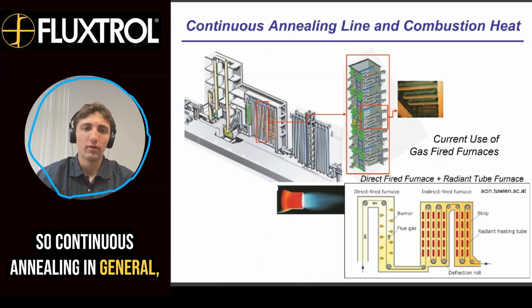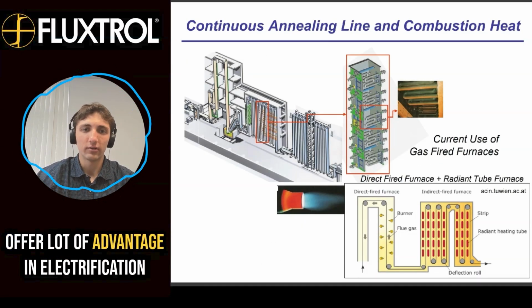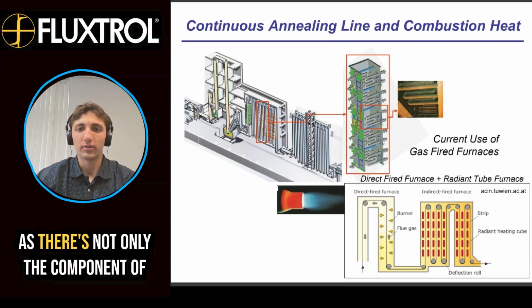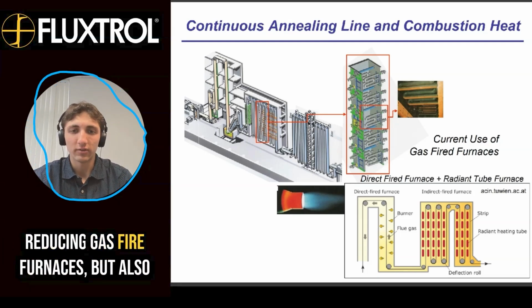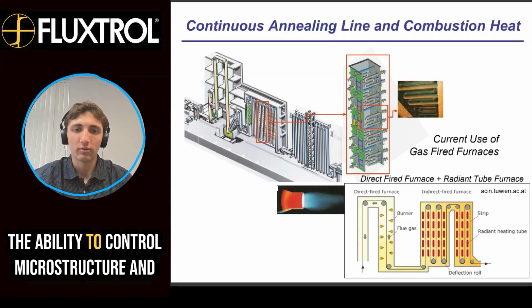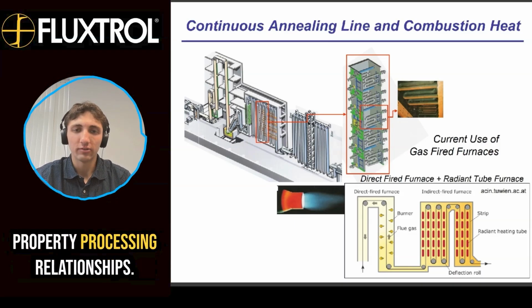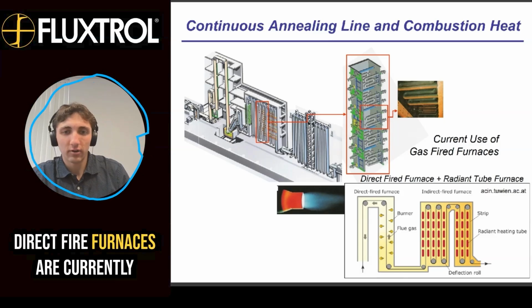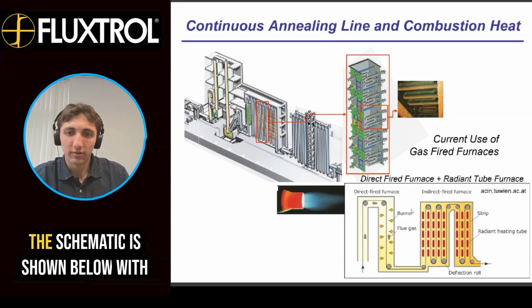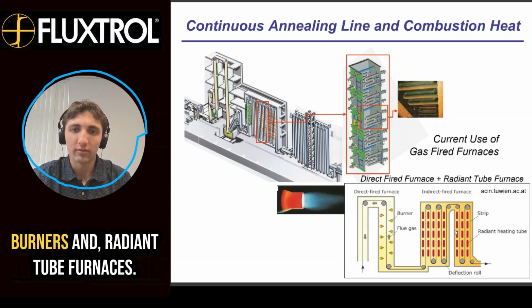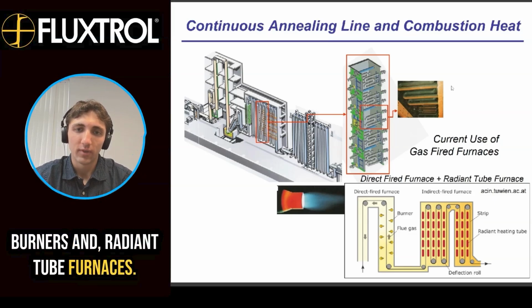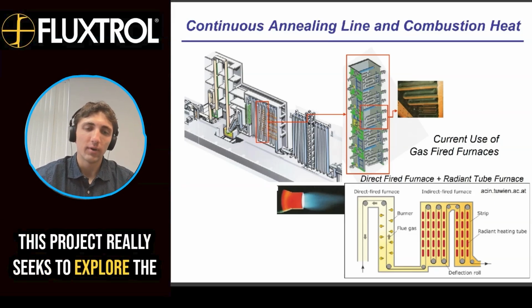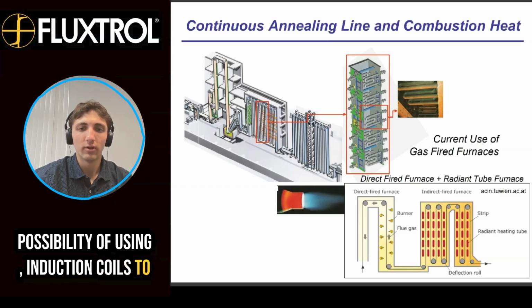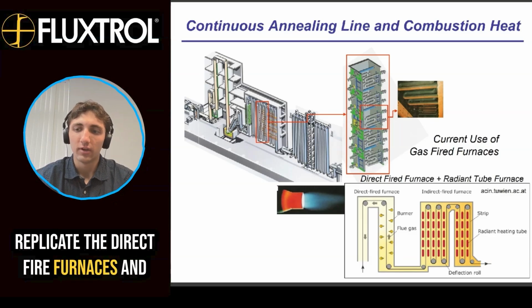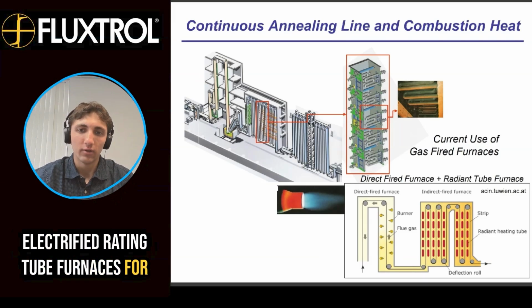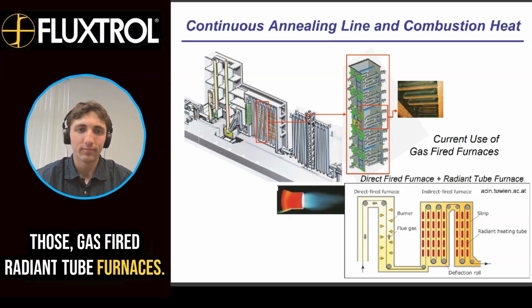So continuous annealing lines in general offer a lot of advantage in electrification, as there's not only the component of reducing gas-fired furnaces, but also the ability to control microstructure and property processing relationships. Direct fire furnaces are currently used throughout continuous annealing lines. The schematic is shown below with burners and radiant tube furnaces. And this project really seeks to explore the possibility of using induction coils to replicate the direct fire furnaces and electrified radiant tube furnaces for those gas-fired radiant tube furnaces.